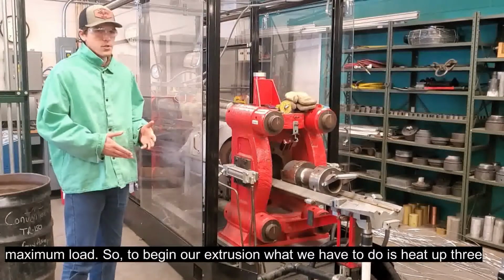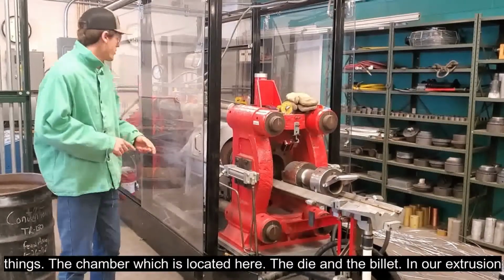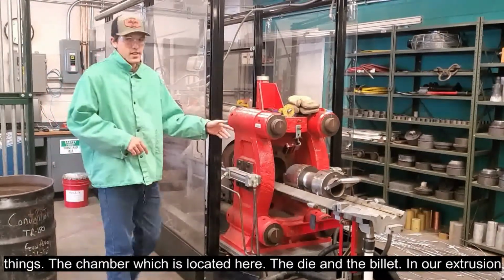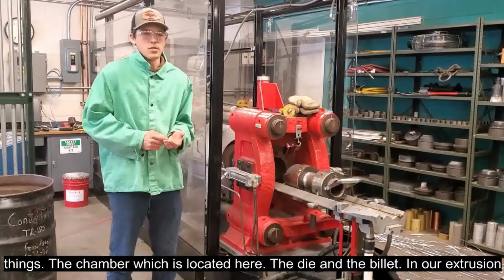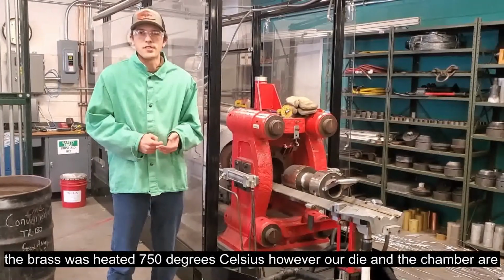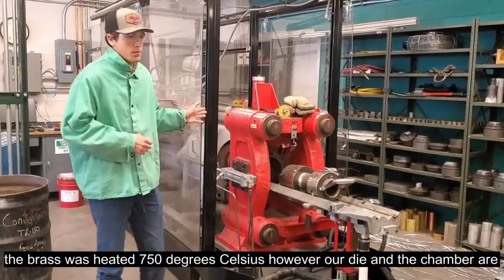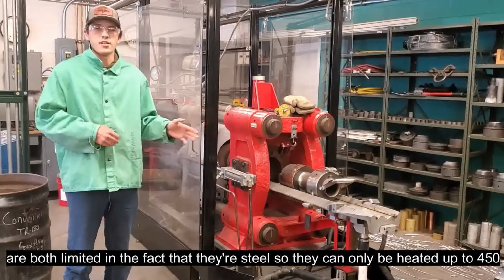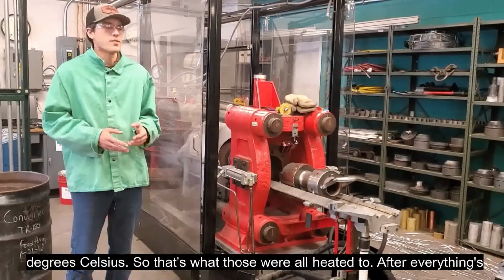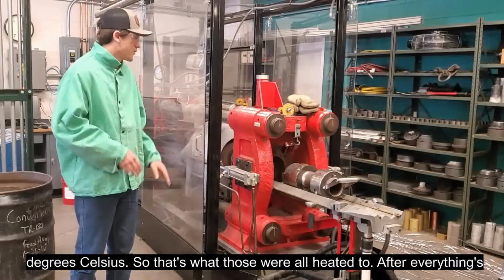So to begin our extrusion, what we have to do is heat up three things: the chamber, which is located here, the die, and the billet. In our extrusion, the brass was heated to 750 degrees Celsius. However, our die and the chamber are both limited in the fact that they're steel, so they can only be heated up to 450 degrees Celsius. So that's what those were all heated to.